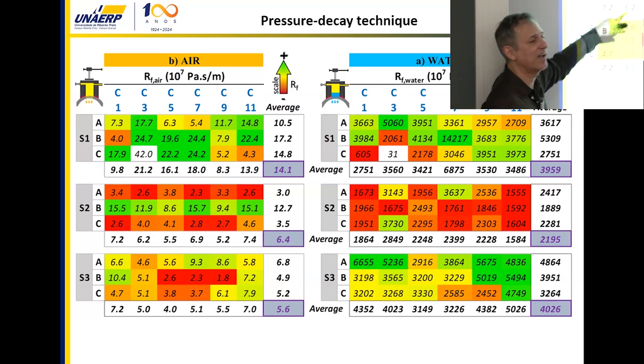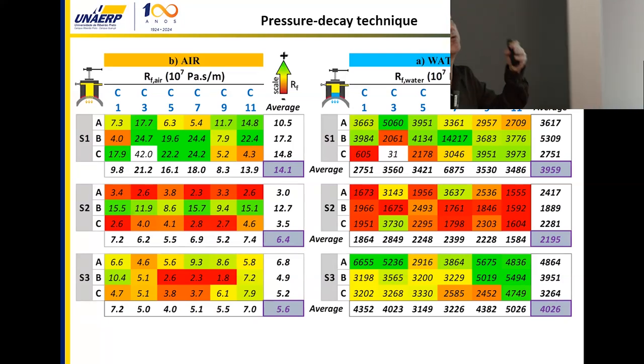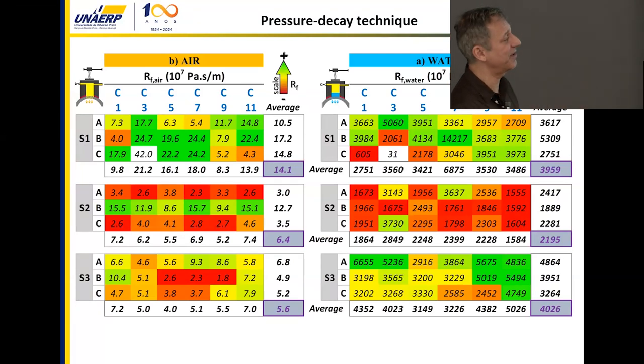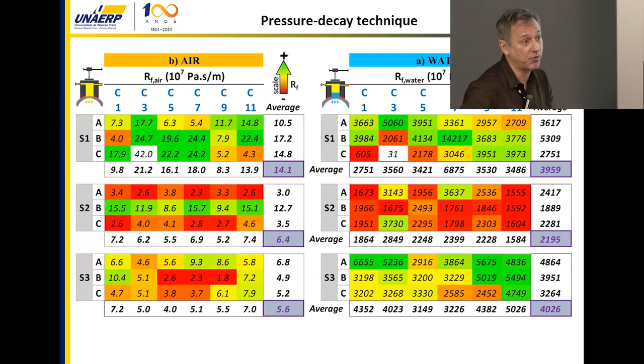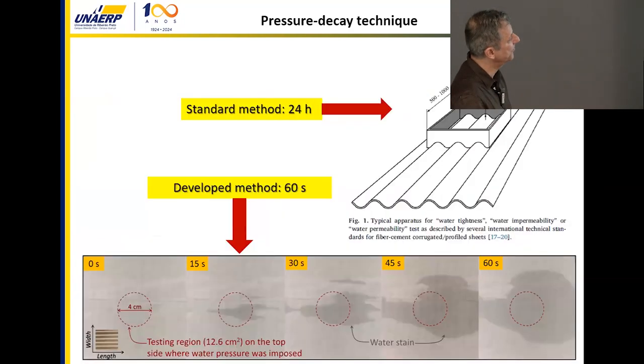green squares are the points with good permeability. Good means low permeability, and you have the red ones with bad permeability, which means that you have a lot of flow. In this case, you don't want to have flow for the corrugated film. And what a standard method gets in 24 hours for a test, we get in 60 seconds using this technique. So it's a very easy and very helpful technique.